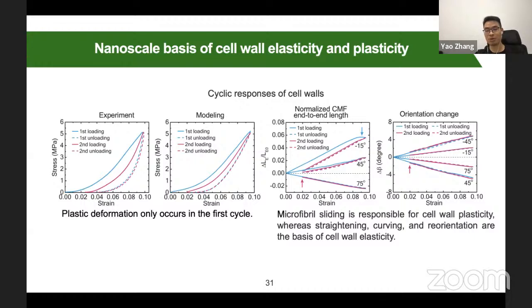Because in the second cycle and in the third cycle, the change of the end-to-end length is the same, and also the orientation change in the second cycle and the third cycle are the same. They are repeatable. So it means that this straightening, curving, and reorientation are the basis of cell wall elasticity. It just causes elasticity. And the plasticity comes from the microfibril sliding.